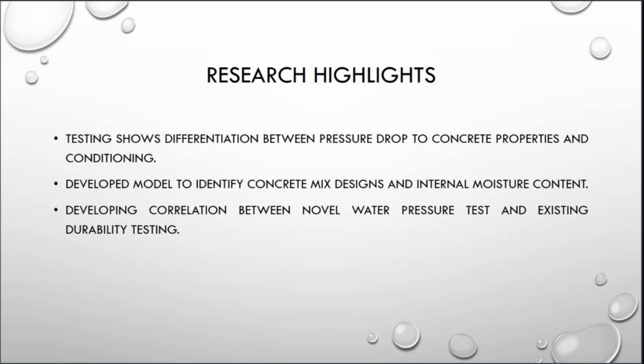So both. The initial phase of this research was to understand the role of the moisture content, because our feeling was that it would affect the measurements and how to interpret them. So in testing, we want to control the moisture content just to understand. But fortunately, with the data, we're seeing that whether it's dry or wet, they have different behavior, which can help us resolve that K factor, which dimensionally is correlated to the initial pore size and how much those pores can be wet. So we're thinking we can attribute it to the pore distribution as well.